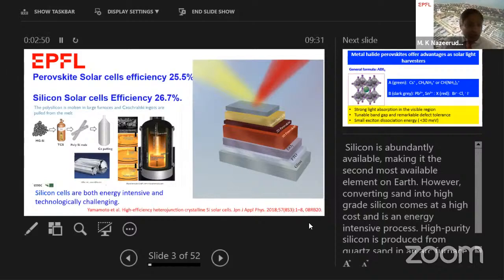All these processes are technologically very intensive, and from the energy point of view, enormous energy intensive processes. On the contrary, look at the right side, where we are comparing the perovskite solar cells. These are cells which you can fabricate by solution processing. So what do you need here? You need only 3 main layers. One is an electron transport layer, typically titanium dioxide shown here on top of conducting glass, or it can be tin oxide.